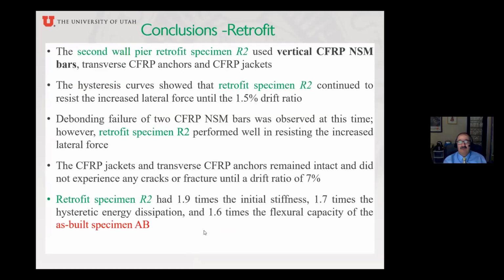How about the second retrofit? To remind you, the one that had the vertical near surface mounted carbon fiber bars. It also had the transverse anchors. It also had the carbon fiber jackets. This one was good up to 1.5% drift ratio on one side, where 2 of the near surface mounted carbon fiber bars debonded. And of course, this can be prevented if you have a very professional crew installing these bars. But on the other hand, it behaved well and resisted the increased lateral force where the near surface mounted bars didn't fail. The jackets and the anchors were intact and did not experience any crack until 7%.